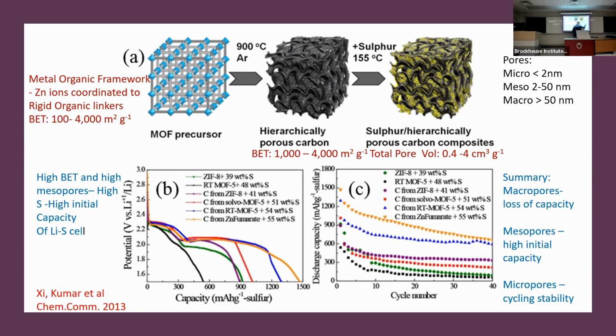But if you have too many very large macropores, the capacity drops very quickly. If you have high mesopores, the 2 to 50 range, then you have a high initial capacity. Micropores give cycle stability. So this is the compromise.